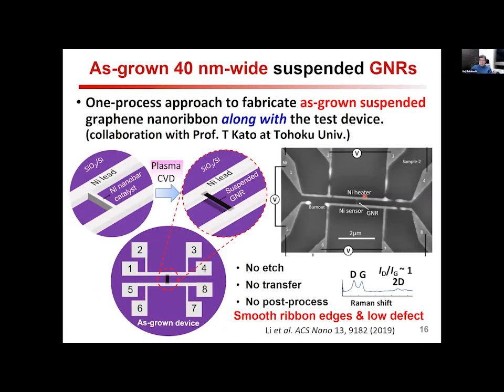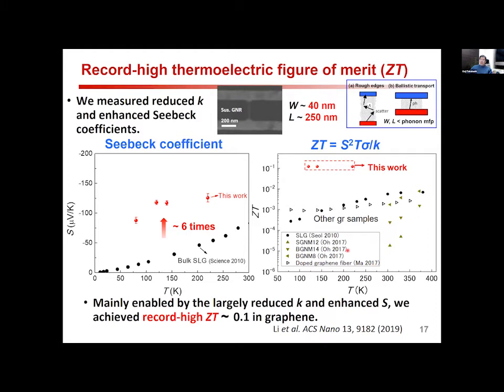And recently, we have fabricated a new suspended graphene nanoribbon, which is much thinner and smaller than the previous one, using a new fabrication process. This process ensures very smooth ribbon edges and also high quality, low defect graphene samples. And we measured the thermal conductivity and Seebeck coefficient and also electrical conductivity to evaluate the ZT, the thermoelectric performance.